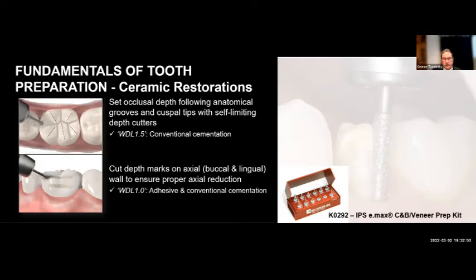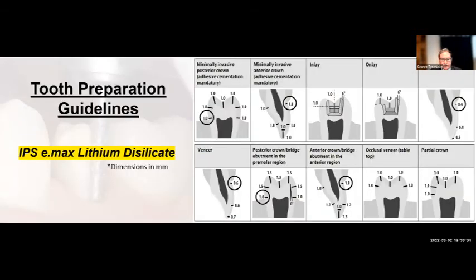And then with the 4Y, we said we go to 1 millimeter, and with the 5Y, at least 1.25, if not more. Depending on what material you have, the reductions have to be adjusted accordingly. For adhesive protocols, there's a difference between conventional cementation, which doesn't reinforce the restoration, and adhesive protocols. For example, on glass ceramics like lithium disilicate, like EMAX, if we're conventionally cementing a posterior restoration, we should have 1.5 millimeters reduction. On the other hand, if we're bonding in place, either with a self-adhesive or a total adhesive cementation protocol, we can get away with 1 millimeter reduction in those areas.